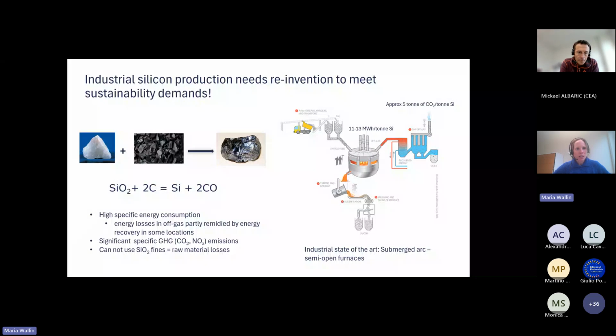And as I guess many of you know, it's a process, or metals in general we are producing with carbon as reductant. And when you put in carbon as reductant, you get out CO and CO2 as an off gas. And this is something we would like to avoid. So what we do is that we charge our furnaces with silica and carbon, and then we put in a lot of energy, and then we produce tap metal at the bottom. Here we tap metallurgical grade silicon. And that's what we are at least working on in this process.